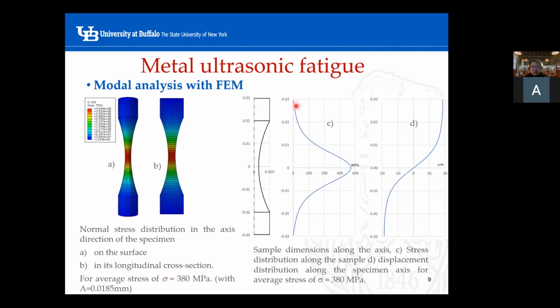And this one shows you the profile of the stress and the profile of the displacement. Again, this stress amplitude is the stress amplitude at the gauge center, and this value must not exceed the yielding strength of the material. The yielding strength of the material, I remember, is around 400 to 410 megapascals. So we have to control the stress amplitude and not let it exceed the yielding strength.